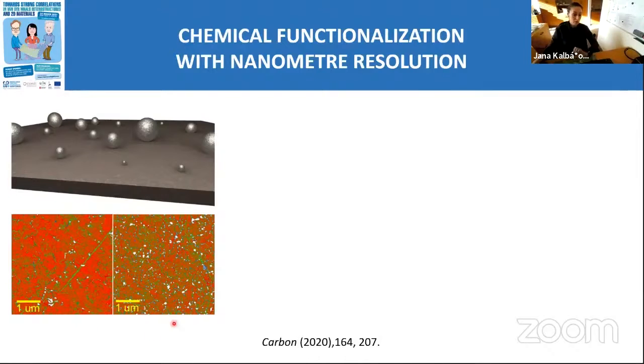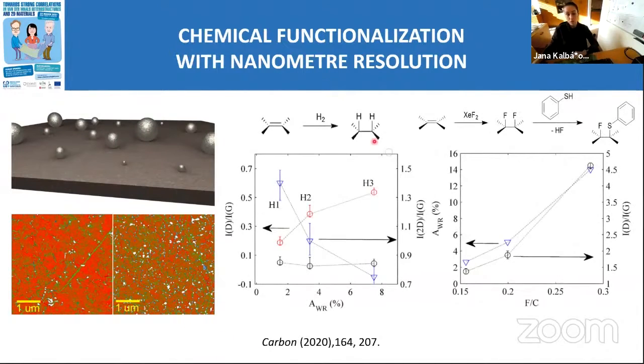So for that purpose, we made the first study on the samples of graphene, which were transferred on a substrate decorated with objects of different size and different distance. So here is some example. And we applied both the hydrogenation and the fluorination procedure. And it can be very nicely traced that with increasing the amount of the corrugations, which is something we can also identify from Raman spectroscopy.